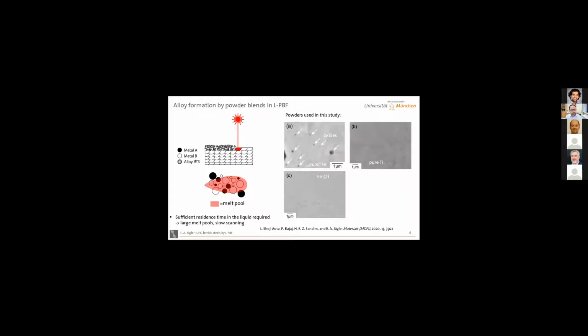Instead of purchasing all of these model alloys from nice companies that produce good results but are a little bit pricey, what we did is to just mix elemental powders. So we just use pure iron, pure titanium, pure aluminum powders, mix them together, and I think by now many groups are doing this worldwide. It has been shown that if you're a little bit careful with parameter selection, in particular, you need to make the melt pool relatively large and go relatively slow, you can get quite nice chemical homogeneity. So that worked also in this case relatively well. I'm not showing you this here, but you can see an example in this paper cited at the bottom.